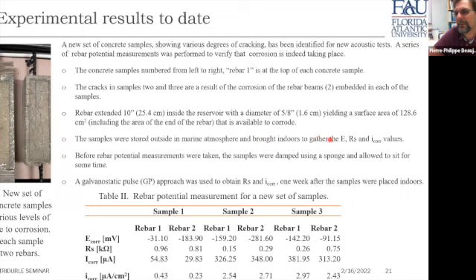and brought indoors to gather the parameters E, R sub S, and I corr, which are measured in the corrosion lab. Now, before rebar potential measurements were taken, the samples were dampened using a sponge and allowed to sit for some time, and a galvanostatic pulse, GP, approach is used to obtain the parameters R sub S and I corr 1 week after the samples are placed indoors.